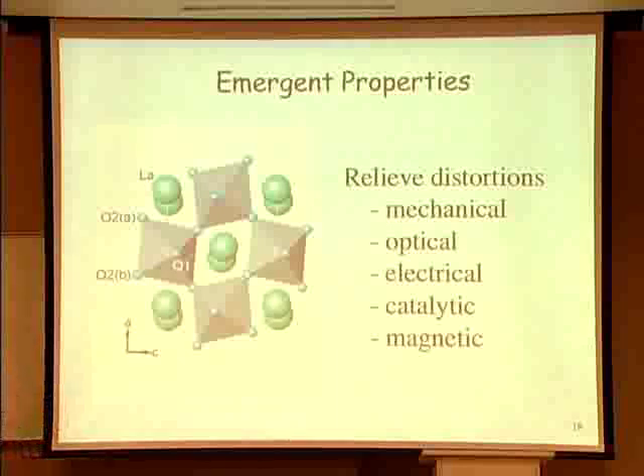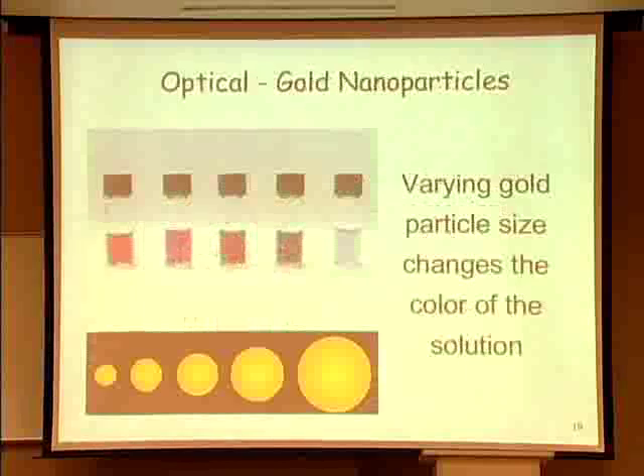Let me give you an example of one of those. If I take gold particles, what color is gold? That's gold. That's why we call it gold. If I make it small, for one thing, it becomes invisible. But when I put a lot of them together in a solution, the color depends on the size. So here are gold particles of different sizes, starting from about 5 nanometers going up to 50 nanometers. And I can go from red to blue. Right? All I did was change the size. I had thought color was intrinsic to the material, and now I show that it's not. It's an extrinsic property. If I get big enough, that extrinsic behavior goes away and it's all intrinsic again. But that's an exciting crossover, going from intrinsic to extrinsic behavior.